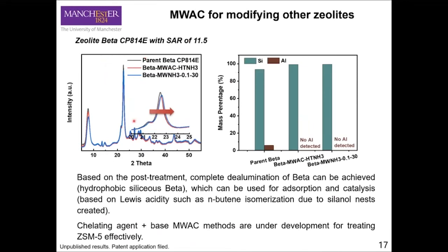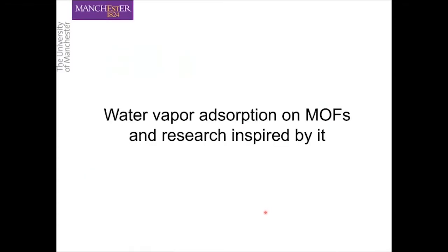For other types of zeolites, for example, the beta zeolite can also be successfully dealuminated by the microwave method. It's quite interesting because after dealumination, you can see the beta zeolite, compared to the parent, is very hydrophobic. It's quite siliceous. Therefore, this kind of beta zeolite can be quite useful for potential adsorption applications in the presence of water vapor. This is something I'm planning to keep working on with SMS later on. We're trying to find time to plan a trip to London to visit the lab over there. And I think that's pretty much a quick summary of my zeolite research.